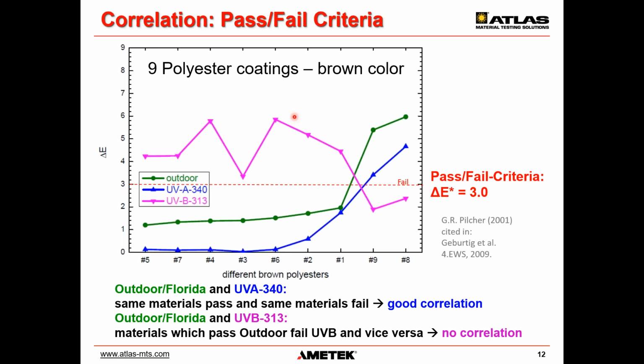You probably also saw this example before, where Florida outdoor weathering for brown polyester coatings is compared to UVA weathering and UVB weathering. For this test setup, the pass-fail criteria was a color change of delta E of 3 or greater. Florida weathering and UVA weathering have the same materials pass the tests. So coating number 1, 2, and so on, the ones on the left side, pass, and coating number 9 and 8 fail in UVA and in outdoor Florida. So the same pass-fail criteria causes the same materials to fail and the same materials to pass the test conditions. So there is a correlation between UVA and Florida weathering.